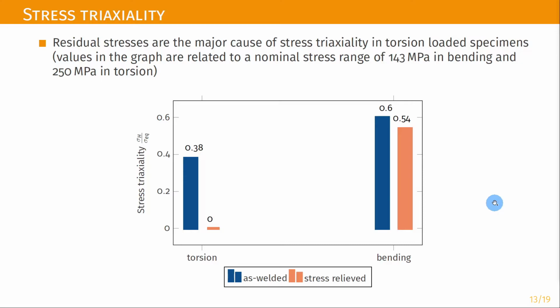As can be seen, in the absence of residual stresses and under pure torsional loading, the stress triaxiality is zero. On the other hand, if residual stresses are present, this will increase. In the case of bending, there is no great difference between as-welded and stress-relieved condition. An explanation could be that during pure bending loading, in the presence of notches, cyclic plasticity stabilized the material and removed part of the initial residual stresses, leading to similar stress triaxiality values.